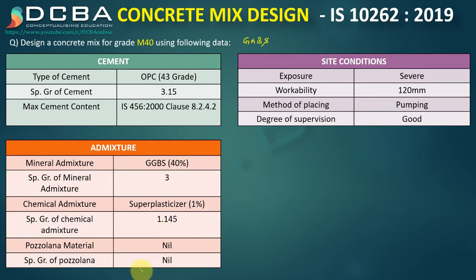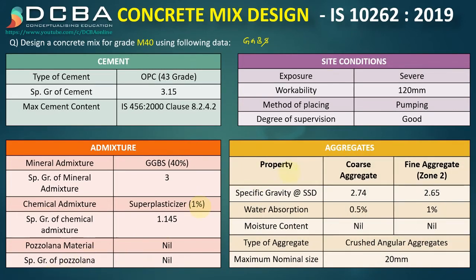The chemical admixture is superplasticizer at 1% of the total cementitious content, specific gravity 1.145. Pozzolanic material is not used. Specific gravity of coarse aggregate is 2.74 and fine aggregate is 2.65. Water absorption: coarse aggregate 0.5%, fine aggregate 1%. Moisture content is not present. Aggregate type is crushed angular, maximum nominal size 20 mm, and fine aggregates are from Zone 2.